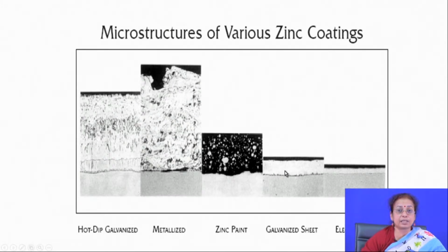Then finally, galvanized sheet. Galvanizing is also mechanical, or maybe you can say that mechanical cladding is also another way of zinc coating. Here you basically take zinc sheet and steel sheet together and then go on cladding them over each other by application of mechanical force. There is always a thickness limitation, because if it is too thick then there will be a problem of non-uniformity. So thickness is limited and the interface is also very strong, but not as strong as in thermal spray deposition, and not really as strong as in hot dip galvanizing.